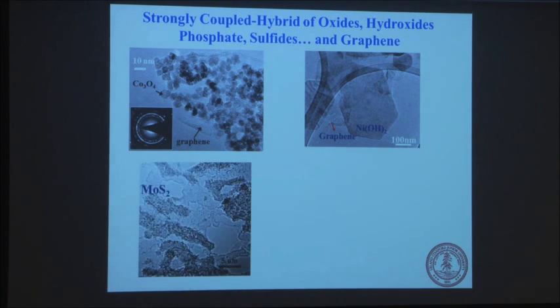One of them is cobalt oxide, okay, particles grown on graphene. And another one is nickel hydroxide, okay, which is a battery material. We can grow them on graphene as well. So it's stacked on the sheet. And another example is moly disulfide, which is a semiconductor and a catalyst. So these are sheet-like structures as well, and they are on top of these graphene, okay? And this turns out to be a catalyst for hydrogen evolution reaction, HER. And the reason it worked very well, we think, is actually because of these edges. You can see a lot of edges in these sheets, and they are not these three-dimensional particles.